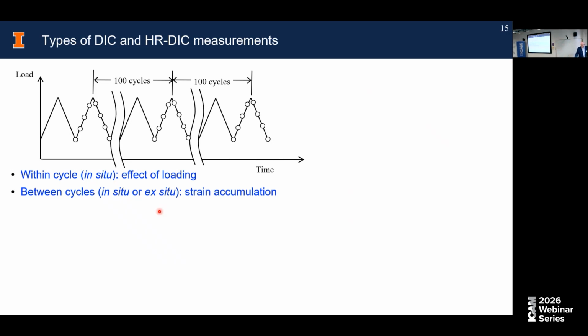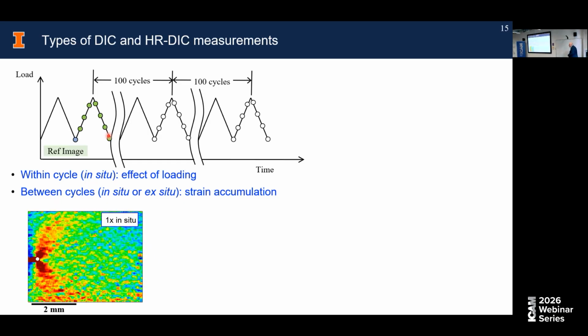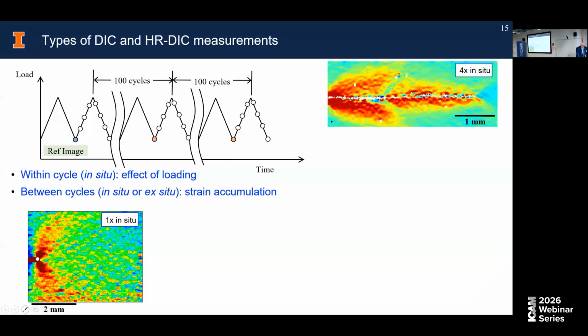But here, thinking of a fatigue experiment, where you have some kind of cycling, you can take images and analyze them within a cycle. So what I think of as in situ, and this would give you the effect of increase and decrease of loading. So you would correlate these green dots with this blue undeformed image, and you would get something like, for a crack, for example, this typical plastic zone here that you would see on the lower left there. Or you can correlate between cycles, either in situ or ex situ.